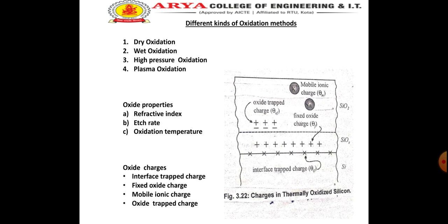The plasma oxidation process involves possibility of growing high quality oxide at temperature even lower than those achieved with high pressure technique. Plasma oxidation is a low temperature vacuum process and it is carried out in pure oxygen discharge. The plasma can be produced by two means: by means of a high frequency discharge, or by a DC electron source.